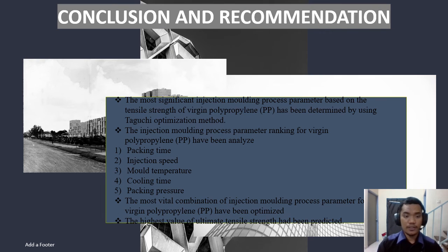In a conclusion, there are 5 process parameters in injection molding, which are cooling time, packing time, injection speed, mold temperature, and packing pressure that had been studied using orthogonal array from Taguchi method. Then the ultimate tensile strength of polypropylene plastic of dog bone specimen had been examined, and all the objective had been achieved. So all I can say that this study is successful.